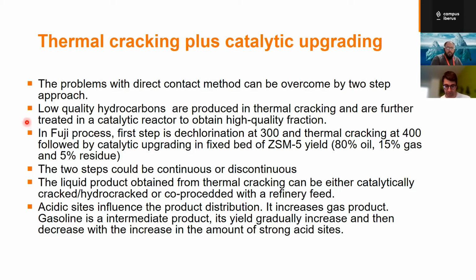So basically, what you do is low quality hydrocarbons are produced in the first step in the thermal cracking, and then you take this into a secondary reactor which has catalyst, and with the help of the catalyst, you can obtain high quality fraction.